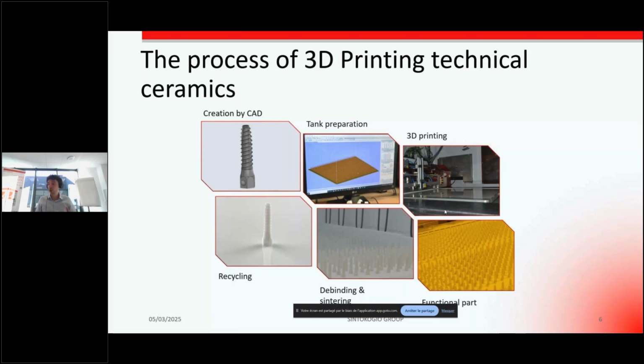After, we have a cleaning and recycling step, in order to save the uncured slurry, which can be reused for the next printing run. And then, as for any shaping process for technical ceramic parts, we have to do two thermal treatments in two different furnaces. First, debinding, to burn and remove the organic contents, and then sintering at high temperature in order to densify the ceramic parts. And it is only after the thermal treatments, debinding and sintering, that we can obtain a functional part which can be used for space, healthcare, semiconductor, and so on.